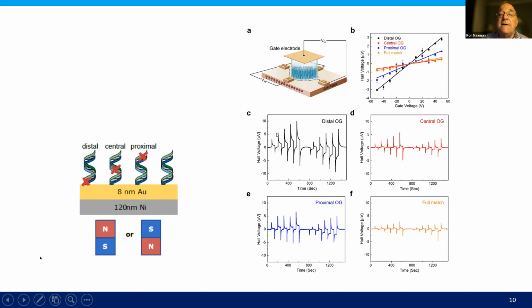These molecules we got from Cynthia Burrows from the US. And as you realize, when we apply the voltage, we get a potential here. And actually, it's summarized, we think that the potential depends on the voltage, but also depends on the damage in the DNA. So why is it important? Because it tells us that the polarizability of the DNA and the spin polarizability depend on the damage. The damage here is oxidative damage of the G base, and this damage not only affects the polarizability and spin polarization, but its position also affects the polarizability.